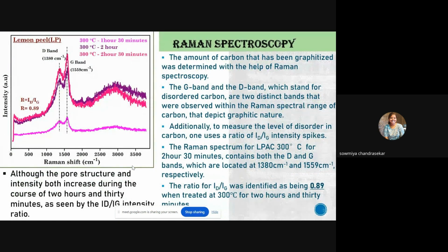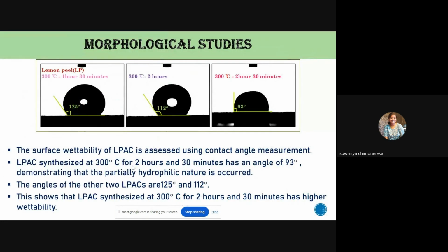Then we come to Raman spectroscopy. The amount of carbon that has been graphitized was determined with the help of Raman spectroscopy. The G band and the D band, which stands for disordered carbon, are observed in the Raman spectra. The ratio for lemon peel activated carbon at 2 hours 30 minutes is 0.89, which is comparatively higher than the other 2. Then we have taken contact angle studies to measure its wettability.